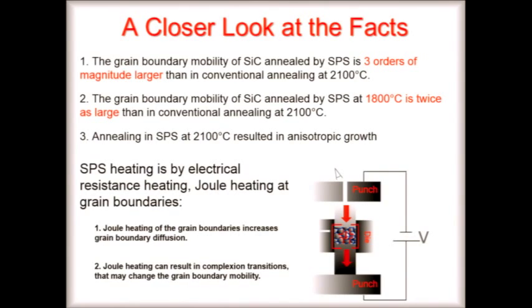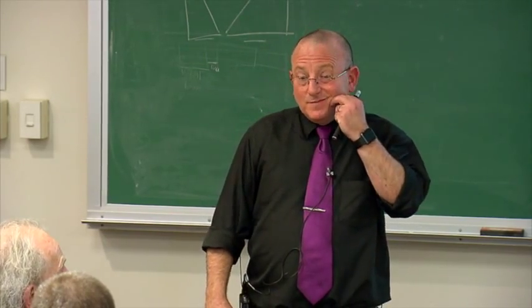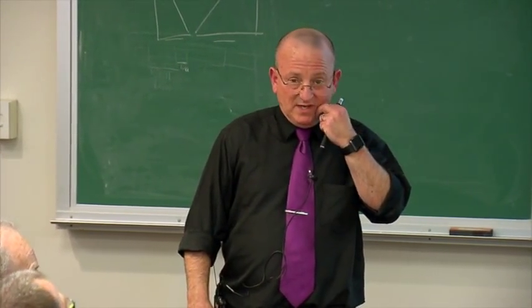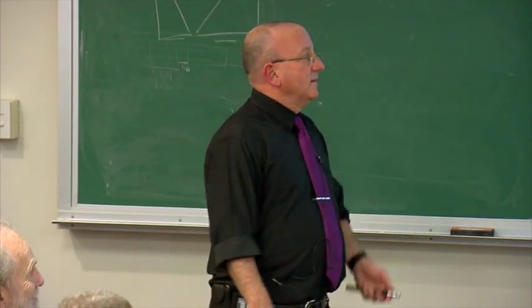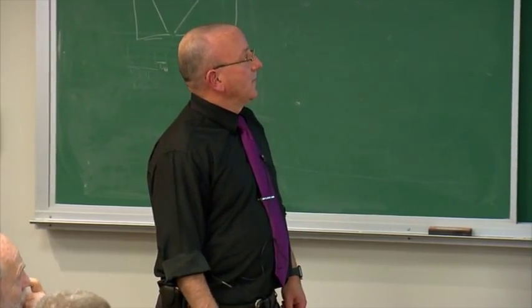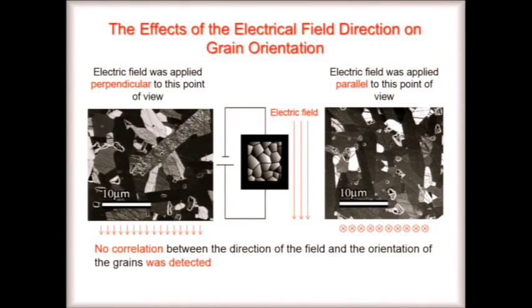My interpretation is in a way that's very similar to what I showed you with calcium going to grain boundaries in alumina and affecting the kinetics of the mechanism. We're doing the same thing here, but with an external field. But that's as far as I've gotten. That's speculation. I can't prove that to you. But given the emerging influence of SPS and flash, then I think that this is something that we need to get a handle on.